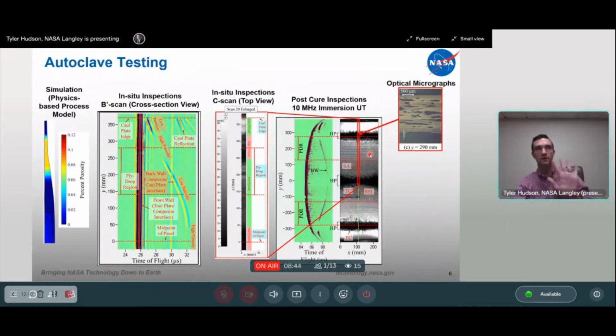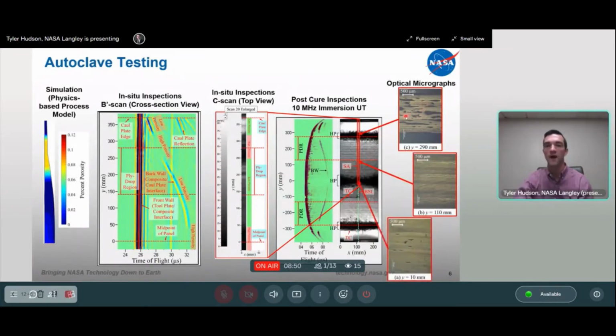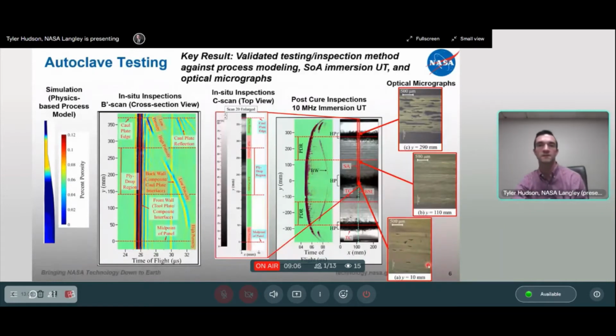We looked at the through thickness section, put it under a microscope, and showed those three areas. And you can see the high porosity corresponding to this area with the very low amplitude, the low porosity corresponding to high amplitude, and then the moderate porosity in the center, which is really what this shows is that we're able to detect even very low percentages of porosity using this system.